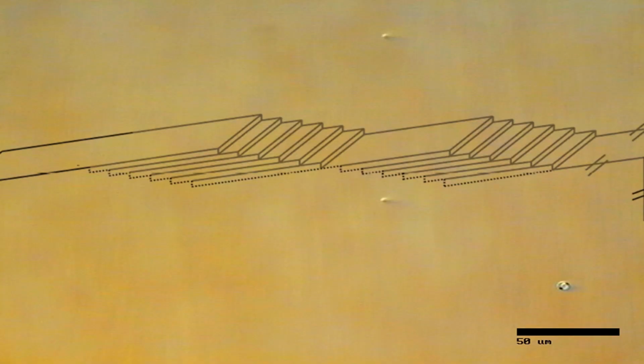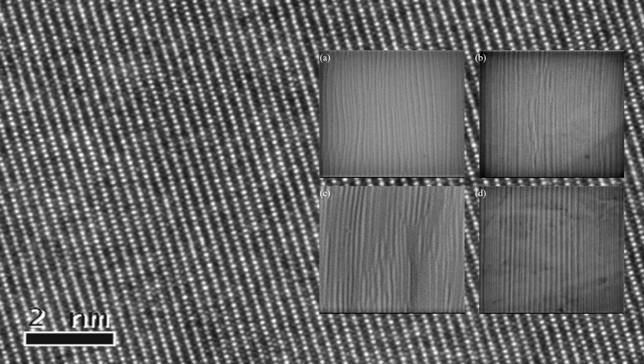And also we explored the surfaces because they must be smooth in order to realize devices. So in the growth, there is step bunching and step flow growth, which are the natural growth mechanisms. So we explored that also and studied, using AFM, atomic force microscopy, the surfaces of these materials, and also TEM to see even more details, and so on. And that was very nice from that point of view.